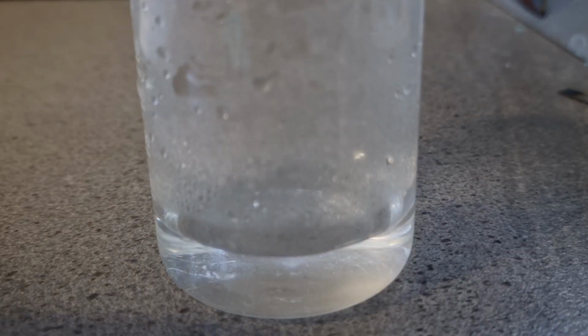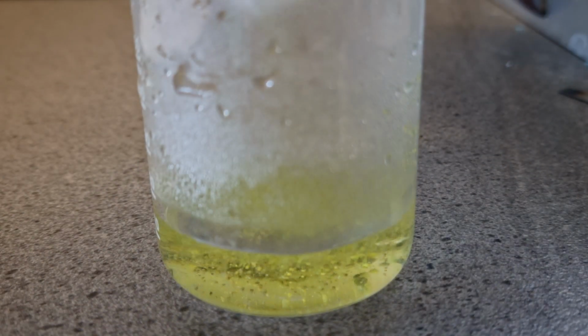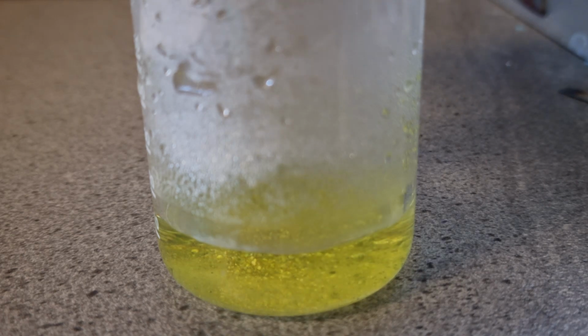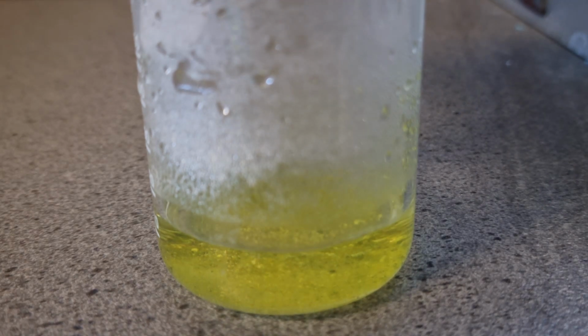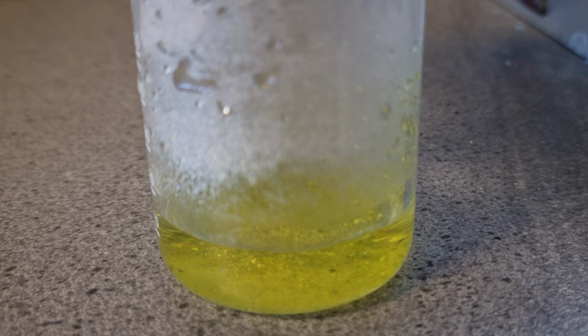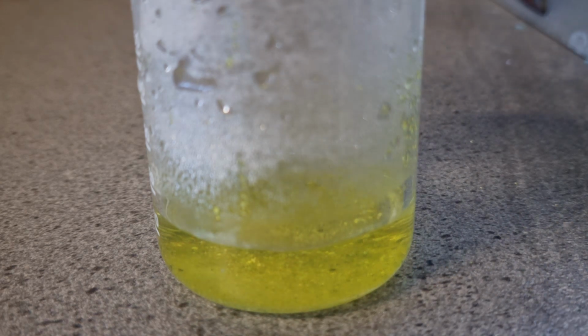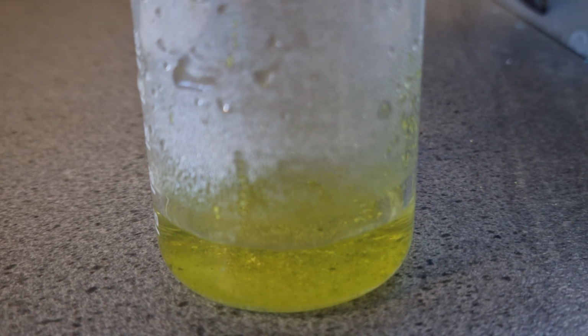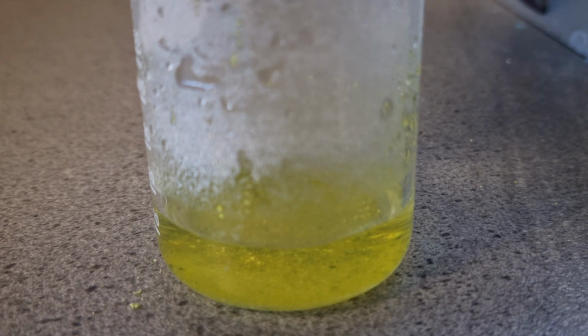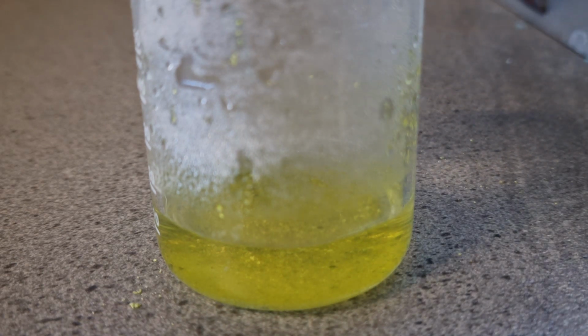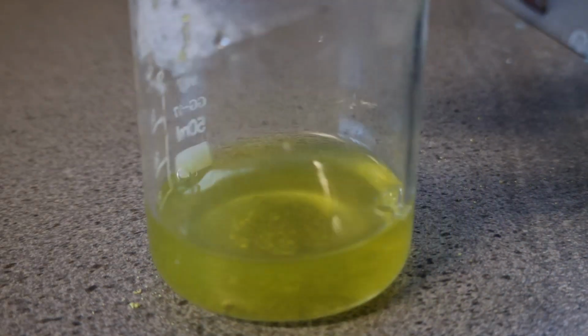The resultant product contains mostly sodium chromate with some unreacted sodium carbonate and chromium 3 oxide. The green chromium oxide is easily separated by dissolving the products and decanting or filtering out the non-soluble oxide. The sodium carbonate can be fractionally crystallized out as it has significantly less solubility than the sodium chromate, or it can be neutralized with an acid, or the sodium chromate can be converted to dichromate first.